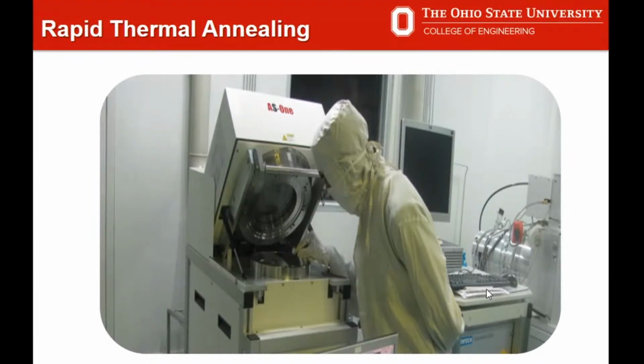And another thing, as I mentioned, temperature and the duration are the 2 most important parameters. And apart from that, what kind of environment are you looking to anneal your samples in? Are you looking for a gaseous environment? It could be nitrogen, it could be oxygen, it could be an inert gas like argon, and it could be even a mixture of nitrogen and ammonia. So you have to be very careful, because depending on the criteria, you have to choose your recipe to anneal your samples.